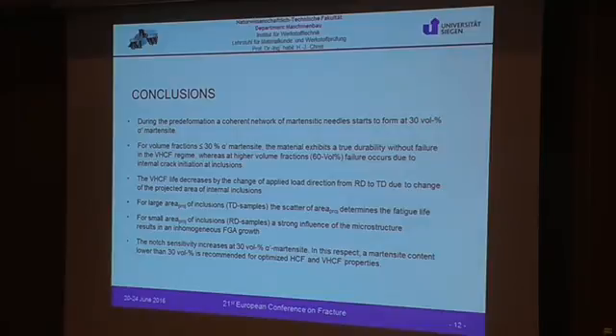I'd like now to conclude my talk. During the predeformation, at 30% martensite, the martensite starts to form a coherent network. For volume fractions at or below 30% martensite, the material exhibits true durability without fatigue failure up to 10^8 cycles, whereas at higher martensitic volume fractions, internal crack initiation occurs and the fatigue life decreases in the VHCF regime. A change of the direction of the applied stress from rolling direction to the transversal direction results in a shift of the S-N curve to a lower number of cycles.